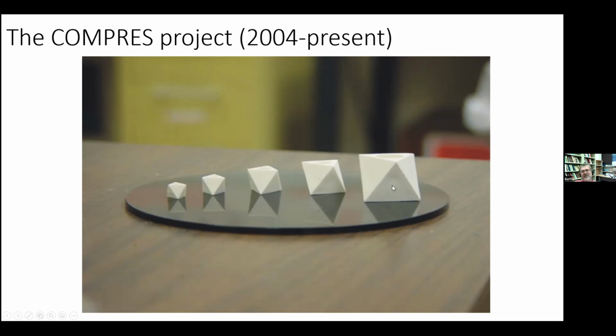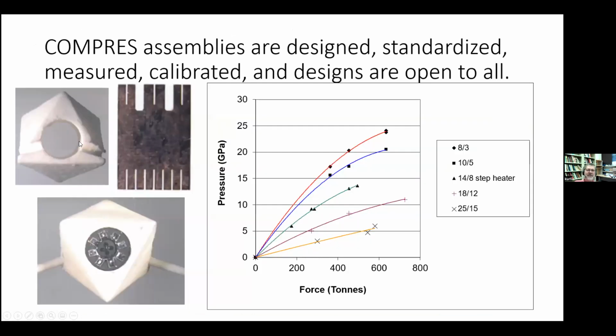And so the pressure ranges would be, this is at least with a 1,000-ton multi-anvil, which is the typical size. This goes to about 6 or 7 GPa. This goes to 11, 14, 20, and 25, and high temperature. Here's the calibration. We provide calibration curves, but we still recommend people do their own calibration because presses can differ. And we've supplied thousands of assemblies per year now to the multi-anvil community.